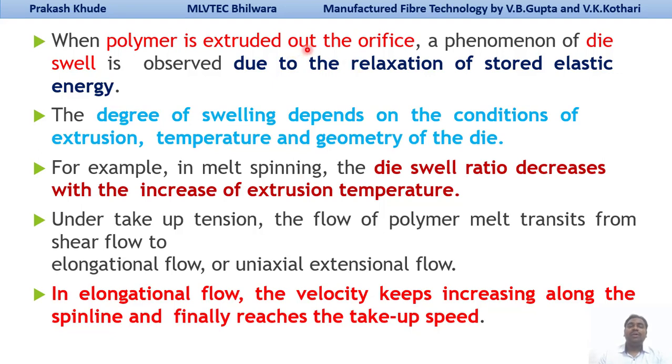When polymer is extruded out of the orifice, a phenomenon of die swell is observed, which is due to the relaxation of stored elastic energy. I will tell you the basic concept of die swell. When a polymeric fluid is coming out of any orifice, there is an increase in the diameter of that polymeric fluid. As in this case, the polymeric fluid is coming out of your capillary. So whatever the capillary diameter is at that point, say small d, when it comes out of that orifice it can bulge out. That phenomenon we call die swell. So there is an increase in diameter at that time.